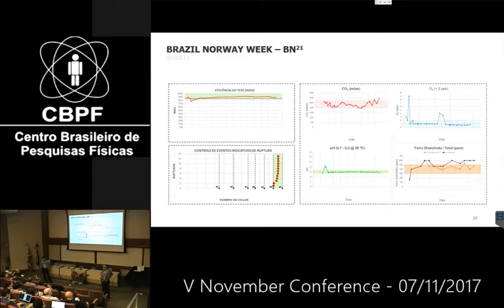Okay, after the test, did you measure the corrosion rates? What was the length of the test? How many months or days? 175 days, more or less 6 months. That's the time that we needed to reach the rupture failure criteria. The deepest attack was 300 microns, so about 0.6 millimeter per year.